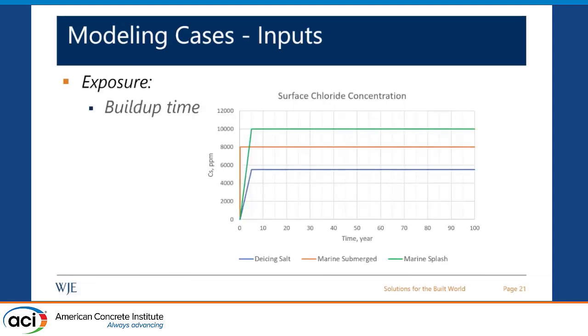For exposure condition, we interpret the maximum chloride concentration as the ultimate value that you would get at the surface, and we used a buildup time of 5 years for the cases of bridge deck with deicing salt, and also for the marine splash case. So it takes 5 years until you get to those ultimate concentrations. For the submerged zone, we didn't assume any buildup times. We assumed that this value is going to be there from the beginning of exposure.